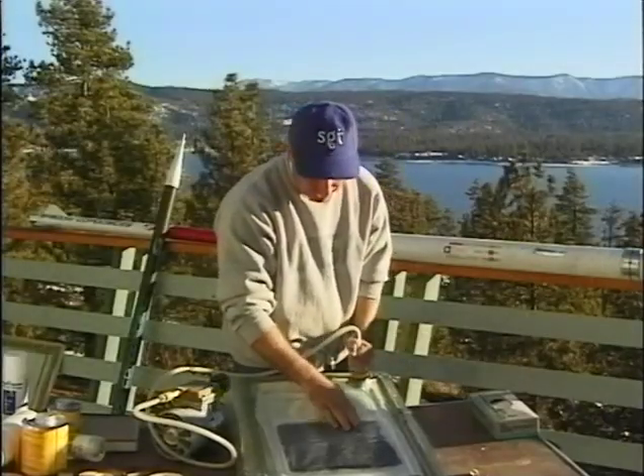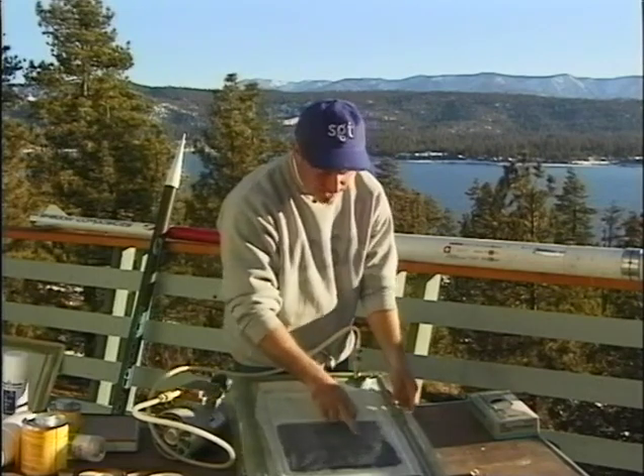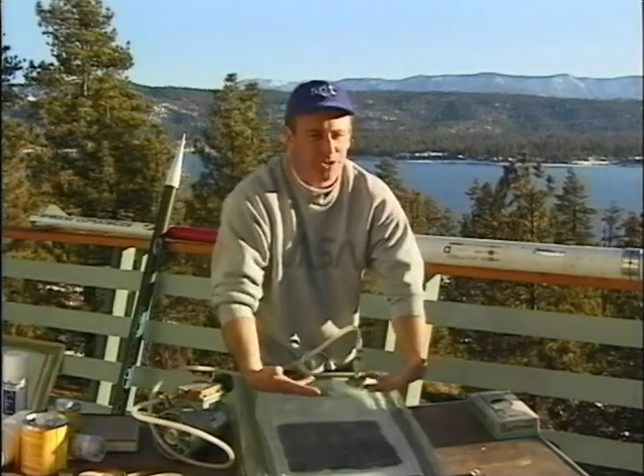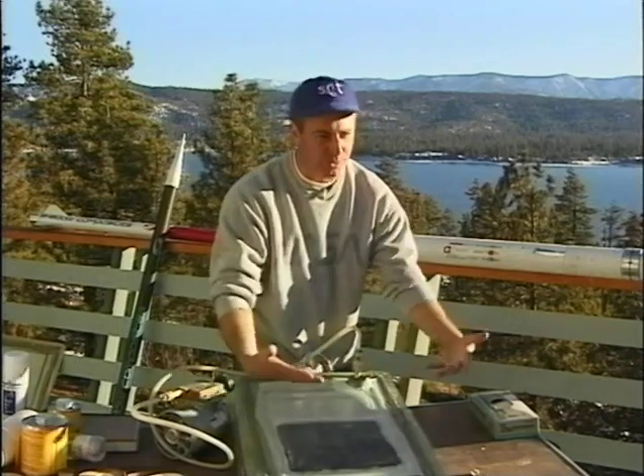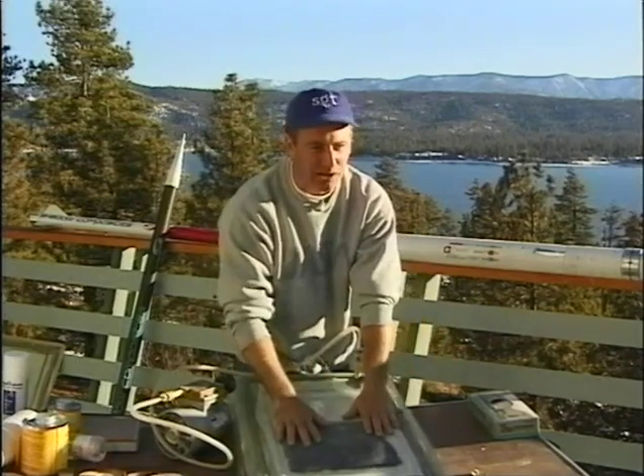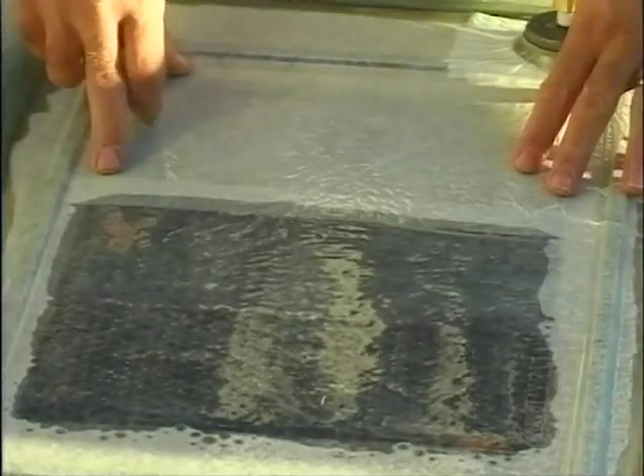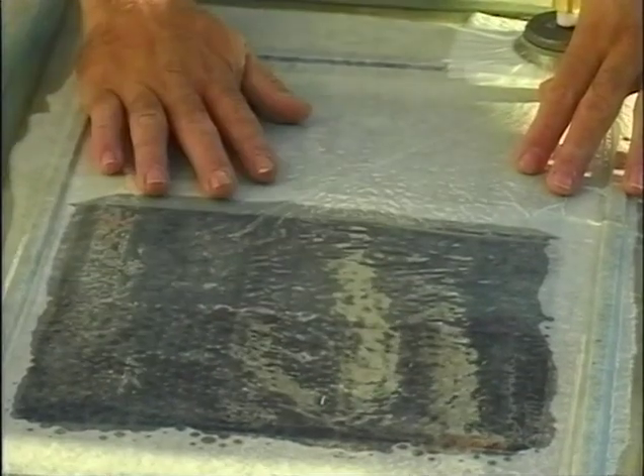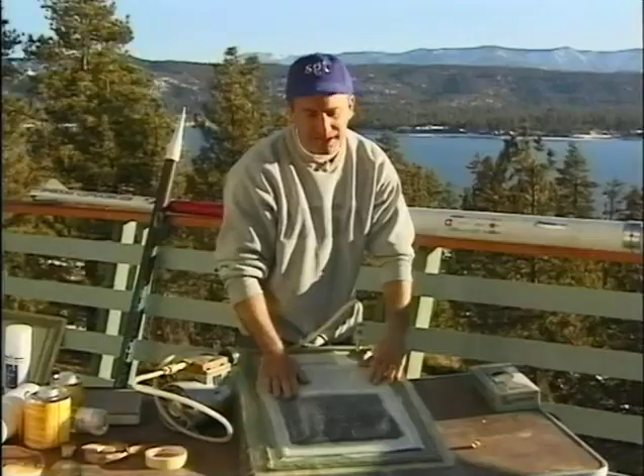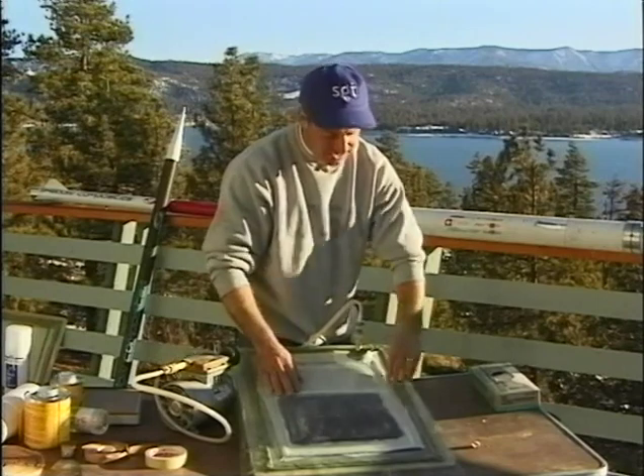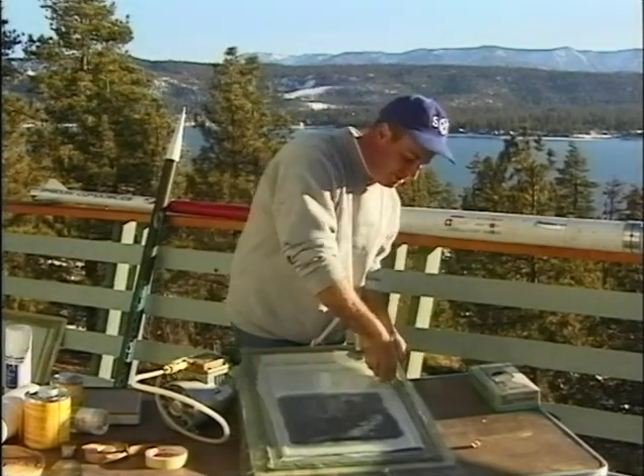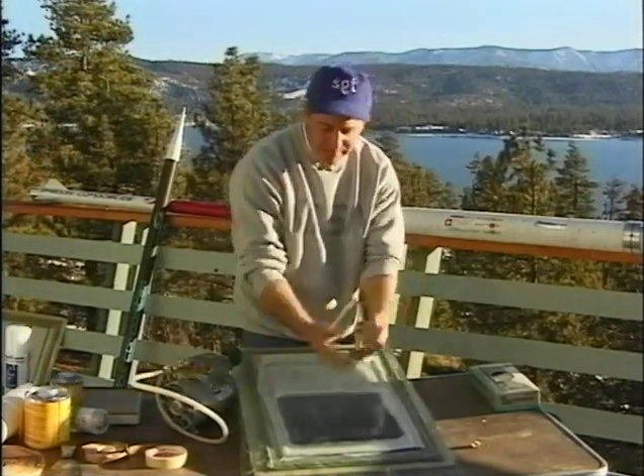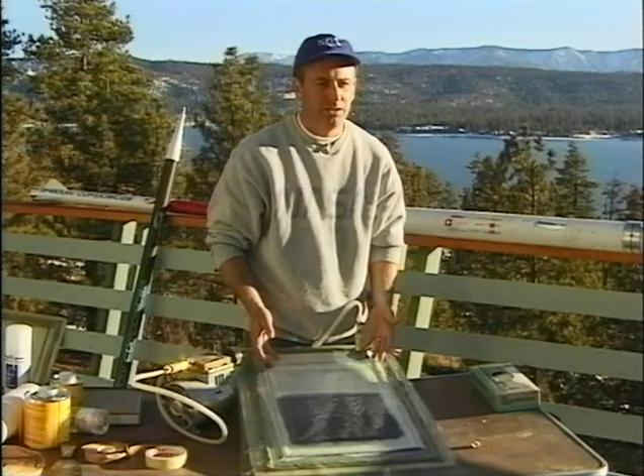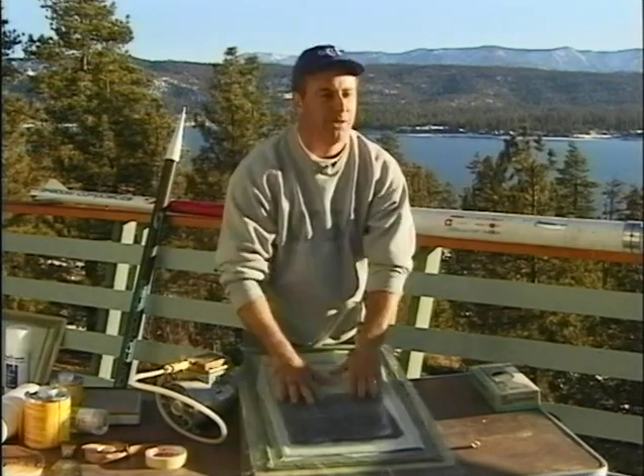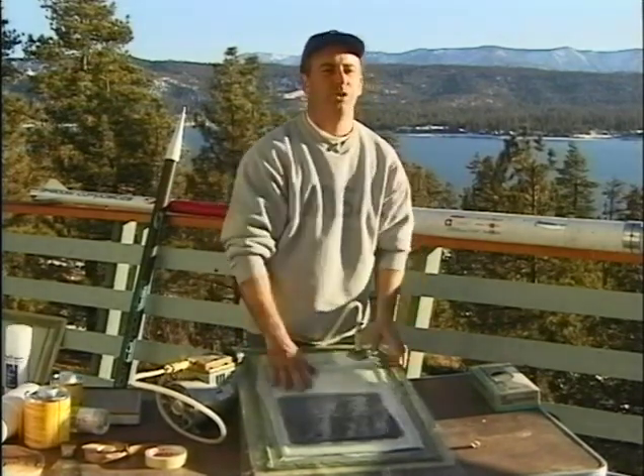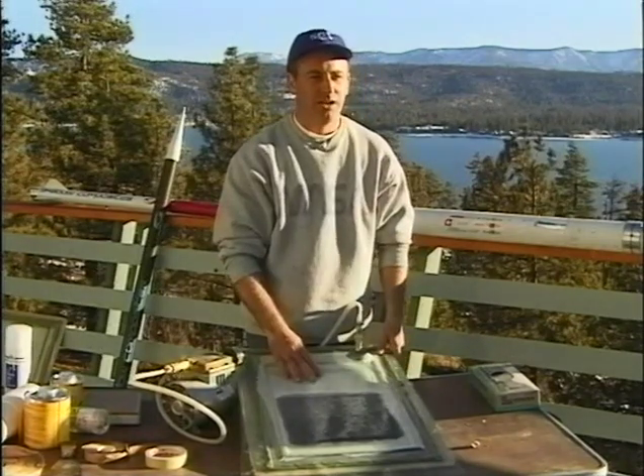In this area is where the peel ply was. So it's coming up in a much more general fashion, just bleeding through the peel ply, and that peel ply is becoming part of the laminate. In this area, there's no resin bleed whatsoever because the mylar is there, and it's going to give that slick surface, okay? You see the bag is down extremely tight. The air is evacuated from this, and the atmosphere is pushing down on it. That's what vacuum bagging is all about.